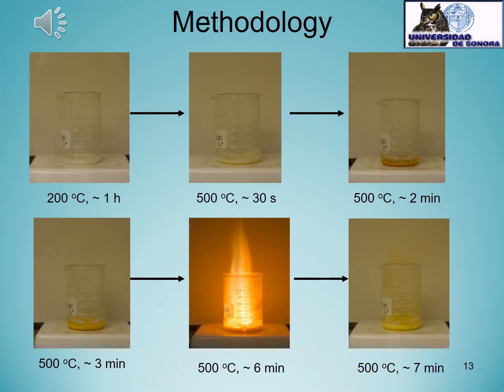Previously to the combustion, we evaporate at 200 degrees Celsius the mixture or the initial solution of the metallic nitrate, which is the magnesium nitrate, and the glycine, and of course the lanthanide salts in the form of nitrates, and in the case of lithium, using lithium chloride. So we stir this mixture during 30 minutes, and then we increase the temperature to 500 degrees.